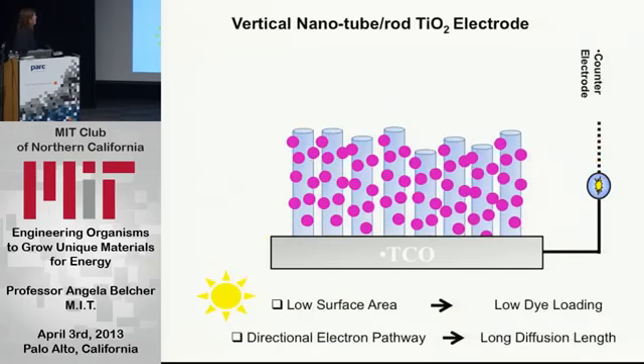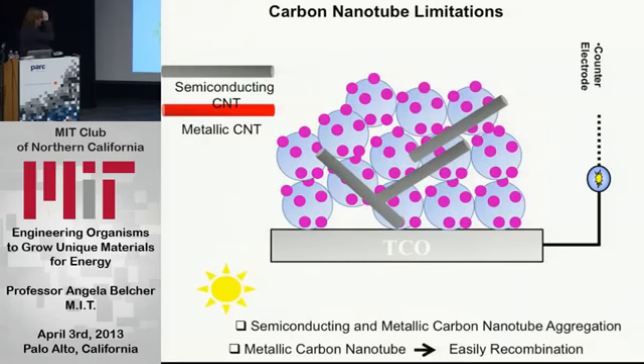You can think about making vertical nanotube structures where you have a lower surface area, so you have lower dye loading, but you have a directional pathway. So in this system, you shine light, and the electrons have a more direct path. And so what my students did is they said, well, we're good at carbon nanotubes now. Let's see if we can put carbon nanotubes in the system. And people had looked at putting carbon nanotubes into the system before, but they were actually getting a decrease in efficiency, not an increase in efficiency.